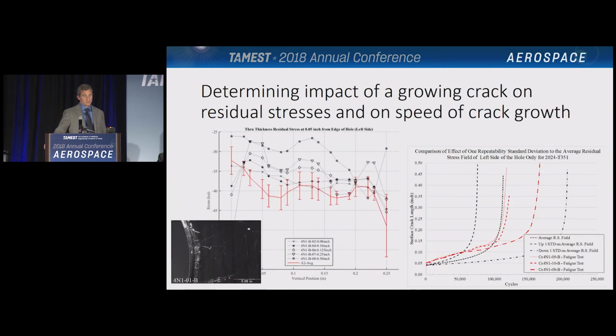So once that was understood for the geometry we were looking at, we had cracks grown in our specimens to different sizes, and then those specimens were cut and the residual stresses measured to see whether the residual stresses change in the part as a crack grows. So the plot on the left shows that they do. The red line, which is the lowest line, shows the stresses through the thickness for the uncracked specimens. Those stresses average about negative 40 KSI through that thickness.